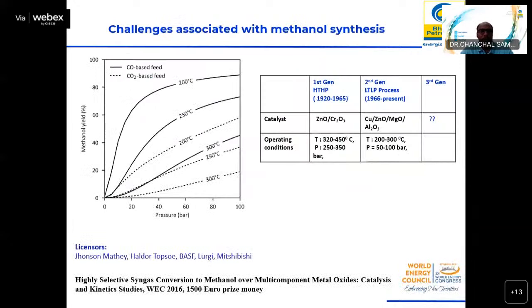So methanol synthesis directly from CO2 is much more challenging than syngas to methanol. And if we look at the methanol yield with respect to the feedstock, CO and CO2, we can clearly see that CO2-based feedstock or CO2-only methanol production has much lower conversion and yield compared to syngas.